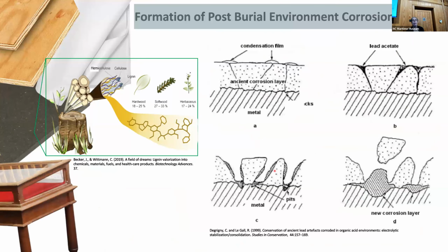And there's also not just products that form in the burial environment, there's also post-burial environment corrosion products that happen in often museum environments. And this has to do with the fact that lead is very susceptible to attack from organic acids. So it is not very soluble in water, but it is very soluble in organic acids, which cause corrosion and dissolution of the material. And a lot of these materials come straight from our own exhibit furniture. They come in the materials that we use to build our cases, our museums. They come from the cases themselves.